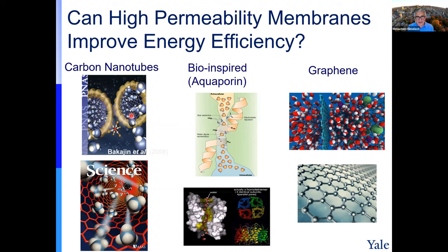We know that carbon nanotubes have a narrow diameter. They are atomically smooth and hydrophobic, and water can go very, very fast through these carbon nanotubes because there is almost no friction. We can talk about aquaporin, the water protein channels that we have in all cells, and they can also transport water at a relatively high rate. And more recently, graphene: if you have just one monoatomic graphene sheet, you can in principle have a very thin membrane that provides very little resistance. And if you have the right holes here, you can get a high permeability membrane.